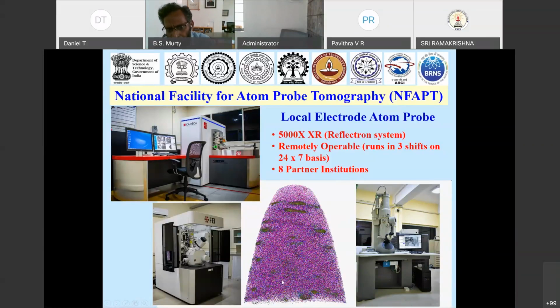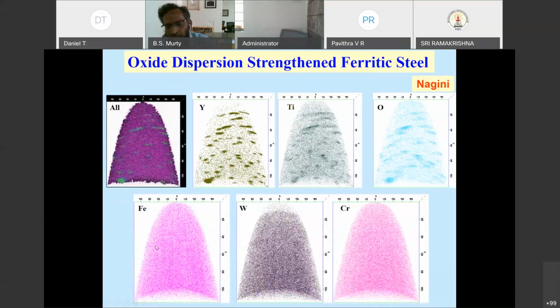And this is one such sample. You can see that iron, tungsten, and chromium are all uniformly distributed inside the sample. But you see yttrium, titanium, and oxygen are there inside the sample in those small particles that I am talking about. Each dot is an atom, so you are able to see atomic resolution of these.